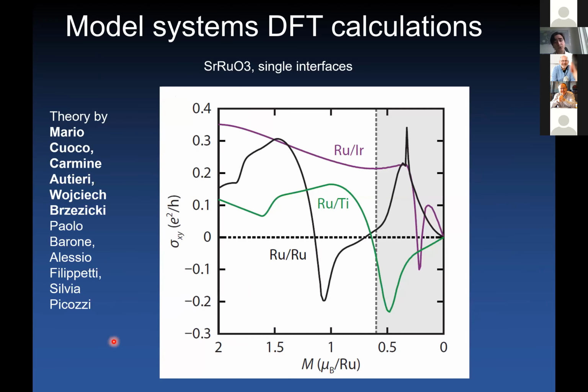And importantly, now if you think of this system in the two-dimensional limit and you put an interface, so interfacing these materials with other systems, you will be able to influence these topological points and control the sign of your Berry curvature. And this was demonstrated theoretically by our collaborators Cuoco, Autieri, and Brzezicki, who were able to show that when you interface strontium ruthenate with a titanium oxide, you will observe a prevalent negative sign of the Berry curvature, while when you interface strontium ruthenate with strontium iridate, you will observe a prevalent positive sign of the anomalous Hall effect.